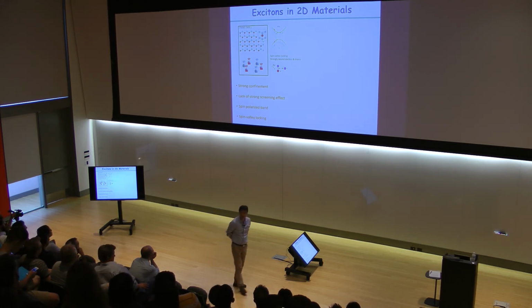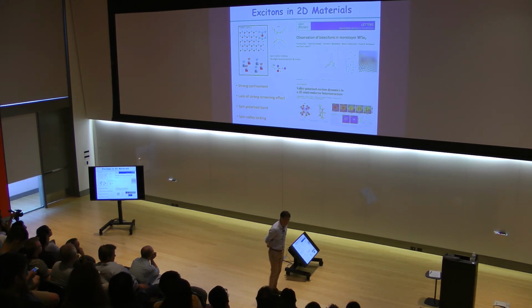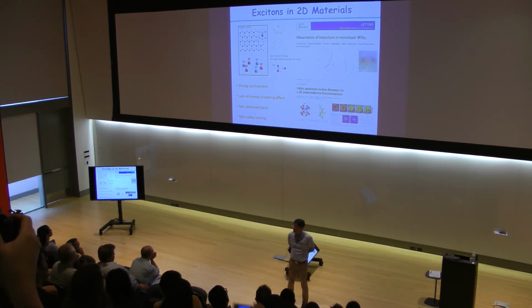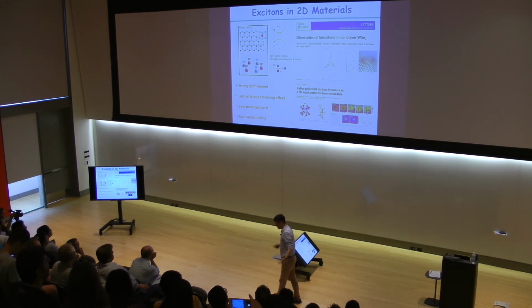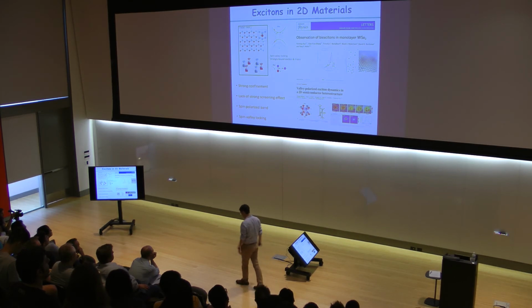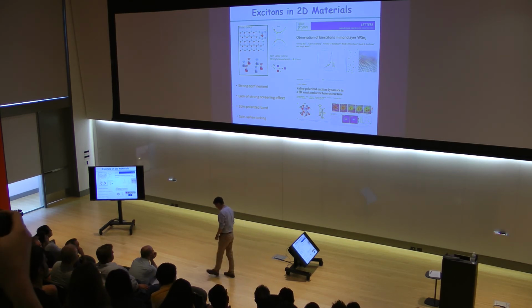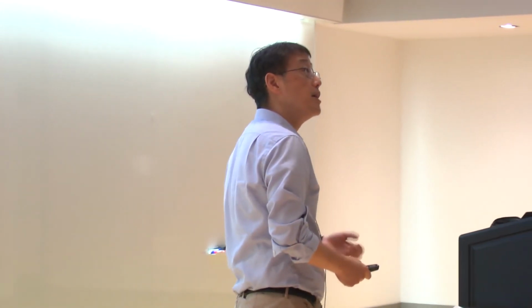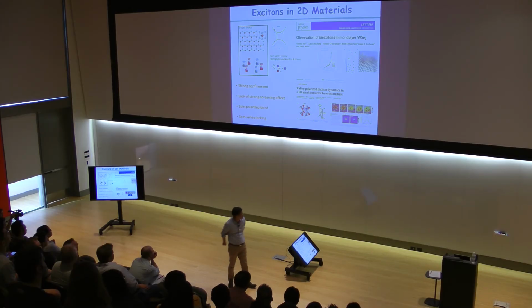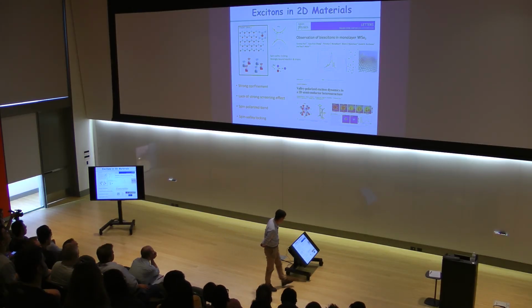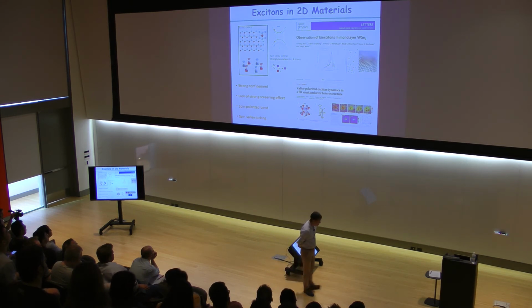This type of beautiful idea has already been tested in two-dimensional electron systems by many other groups. Here are Tony Heinz's group and Xiaodong Xu's group. They all demonstrate that excitons do exist in two-dimensional systems. They are very robust and strongly bound, and you can create many different types of optical species and make interesting coherence. Another interesting part is that strong spin-orbit coupling makes the valleys spin split, which means that using light, you can also control the spin state of these particles or excitons in the system. So we know that this is a very exciting system.